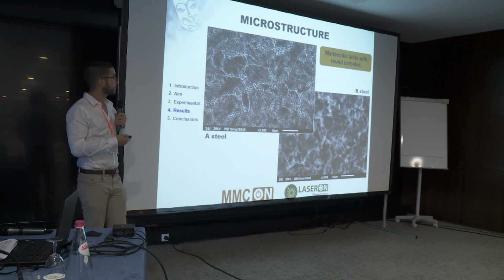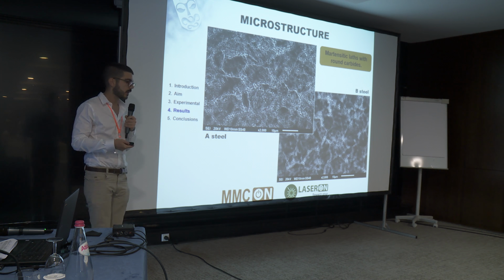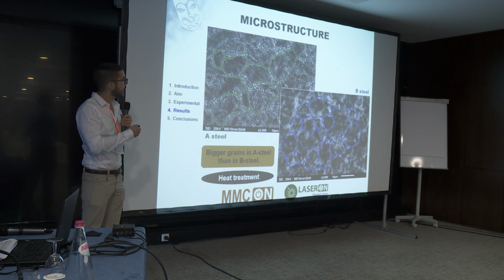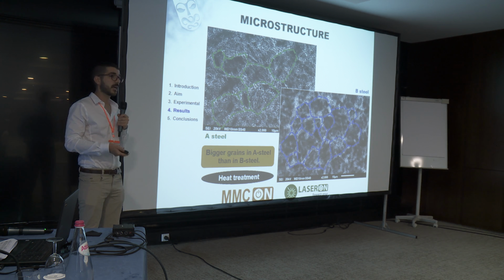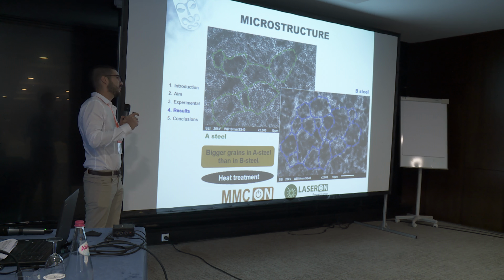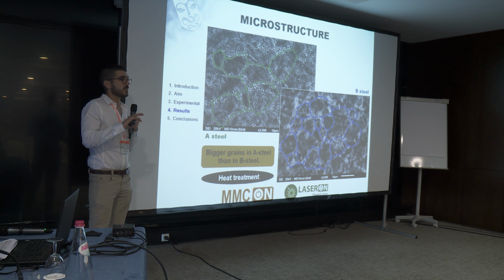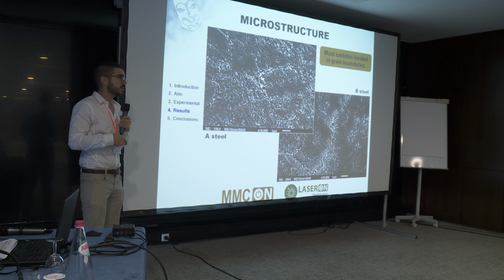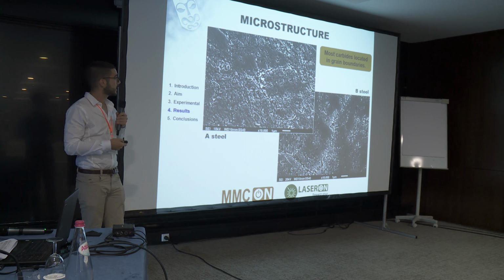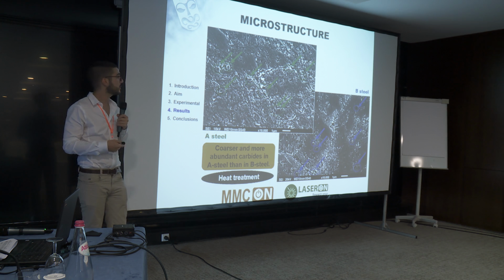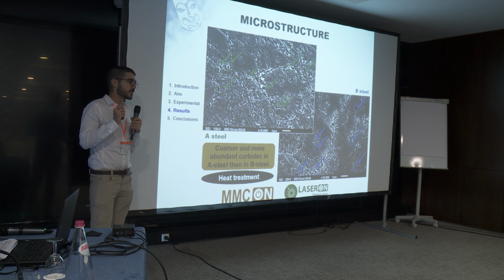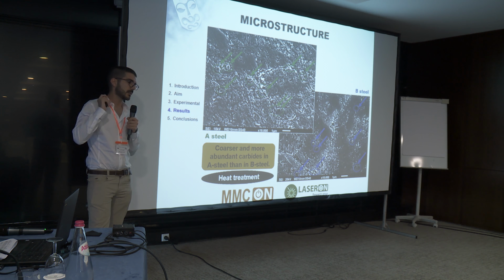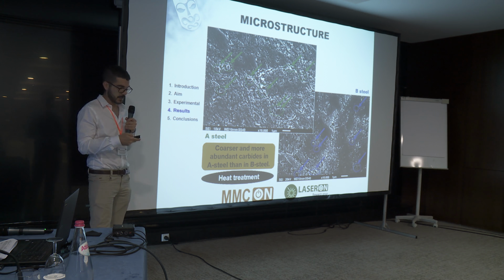What we could see was a characteristic martensitic structure with carbides. The first thing that we observed is that B steel presented slightly smaller grain sizes, which is in line with that small difference that we saw in the tensile tests. At higher magnifications, we were able to see more clearly the presence of carbides, mostly at the grain boundaries, and we could see that A steel presented slightly bigger carbide sizes and more abundant than B steel.